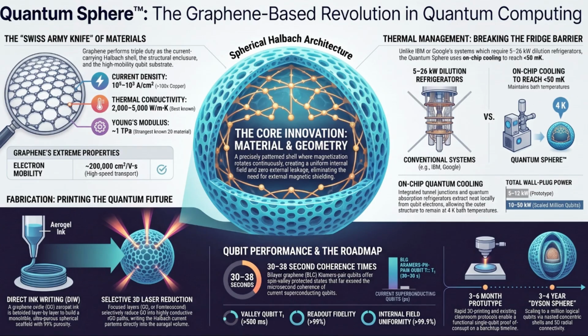Exactly. When the highly focused laser hits a specific spot on the aerogel, it delivers a massive, instantaneous spike of localized heat. This heat provides the exact activation energy needed to violently rip those oxygen molecules off the carbon lattice. The oxygen turns into a gas and escapes through the pores of the sponge. It strips the roadblock away.